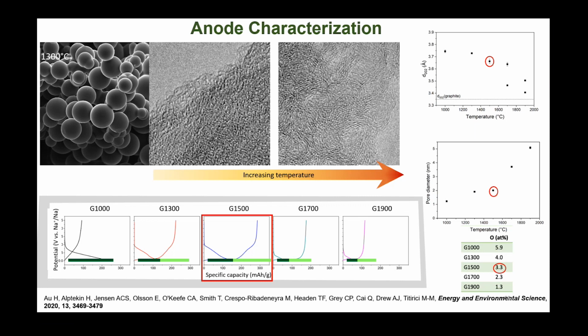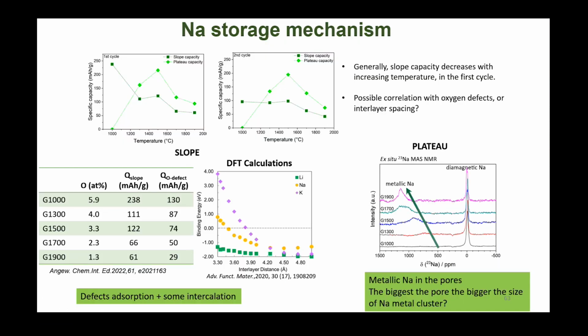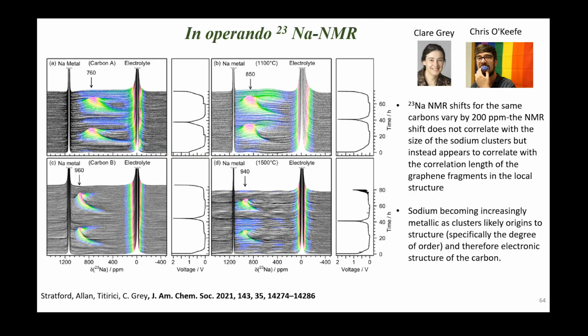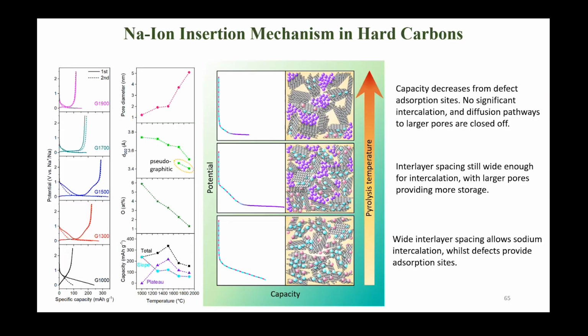You need to have, well, this is more complicated with the pore. In our case, the best material proved to have pores of 2 nanometers, but the microstructure and the pore are closely related. And you also want a sweet spot on oxygen functionalities, or actually other types of functionality, so that the sodium interacts with these defects. And as I said, we did this by a number of techniques, including in operando NMR, PDF analysis, X-ray absorption.